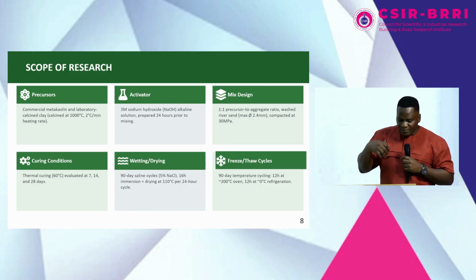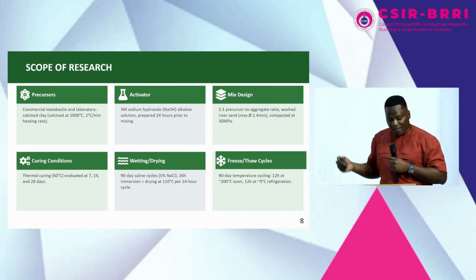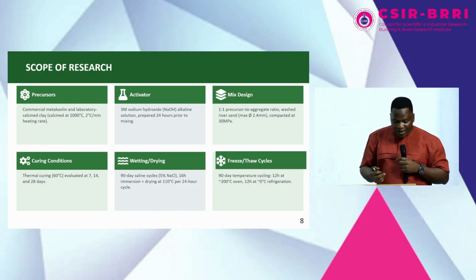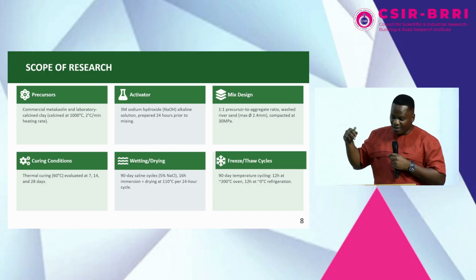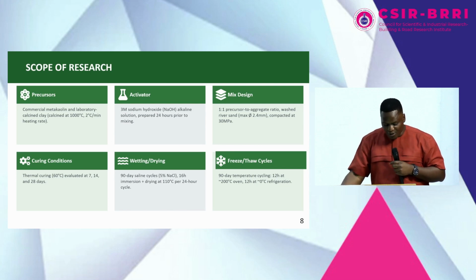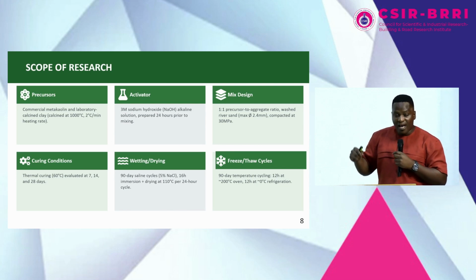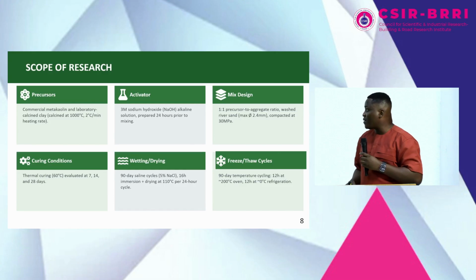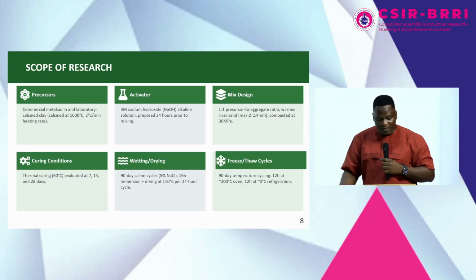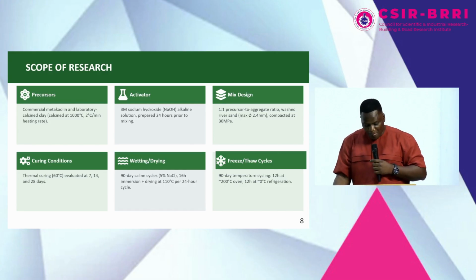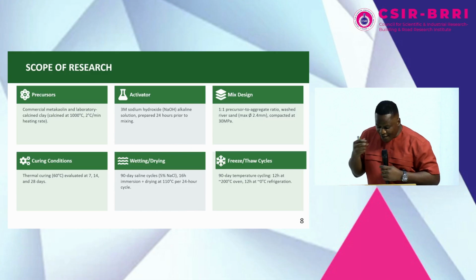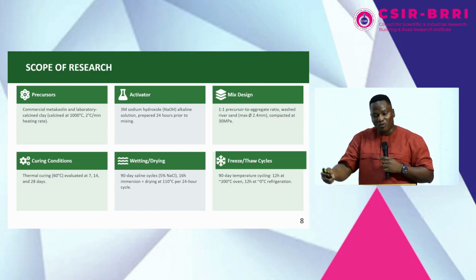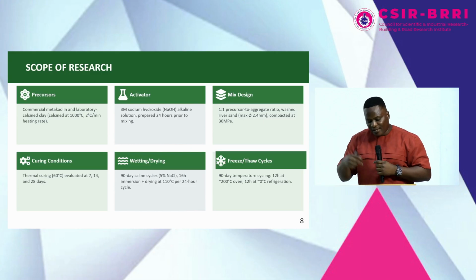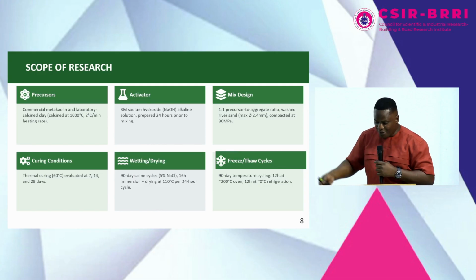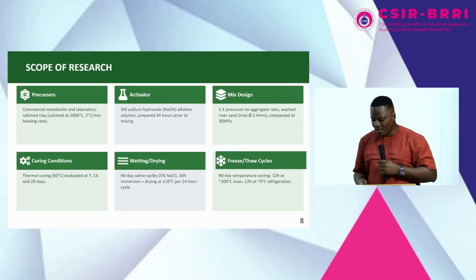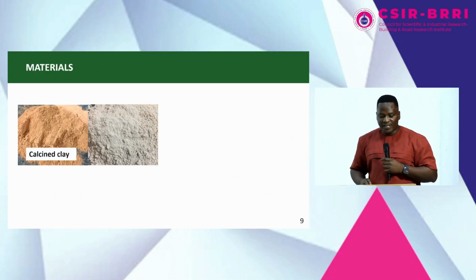Okay, so we have different types of curing, but for this work, it was cured under a temperature of 60 degrees Celsius for 7 days, 14 days, 28 days. But for the purposes of this discussion, we're just going to look at the 28 days results. Then the saline cycle I talked about, 90 days in sodium chloride solution. Then the freeze and thaw cycle, the same 90 days. So these are the materials that we use.